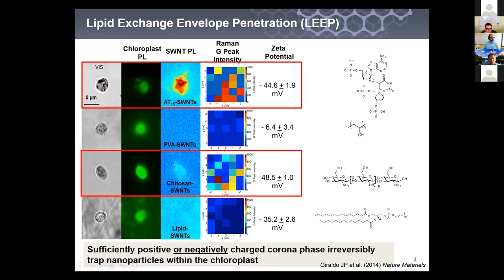So they'll show up. You're supposed to see here the chloroplast, and you see the fluorescence here. Interestingly enough, if you're negatively charged but you're too small, or actually if you wrap the nanotube in the same lipids that comprise some of these bilayer membranes or single layer, you do not get transport. And this is actually an important clue.